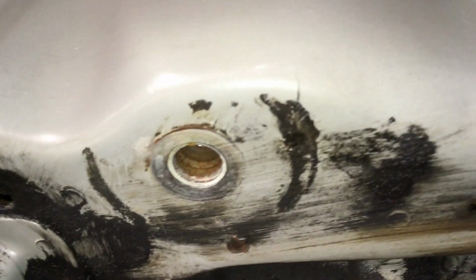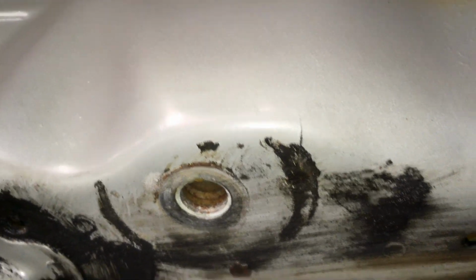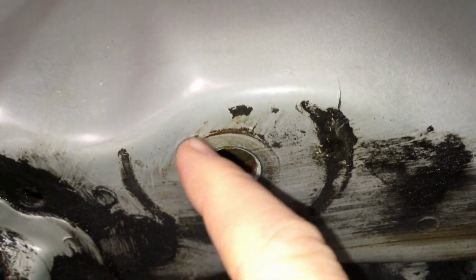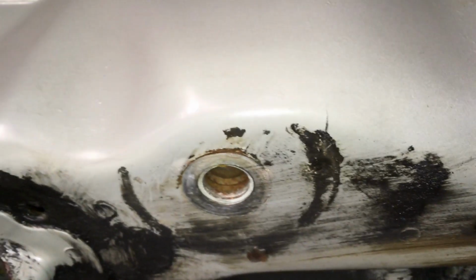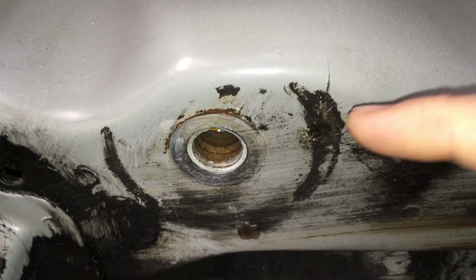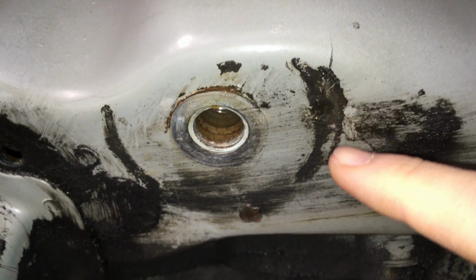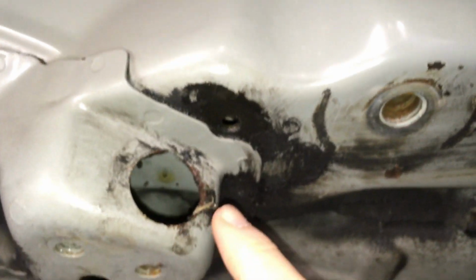We have got a crack on the right front as well. Here's the right front mounting point, a semicircle crack around there. And we've also got a spot weld broken here and a crack coming out up that way, so we might have a little crack going that way. We'll know more once we've cleaned all this. And we've got a little crack around the left front mounting point as well. So we'll clean all this dirt and grease up out into the wheel arches and then assess it properly once it's all cleaned up.